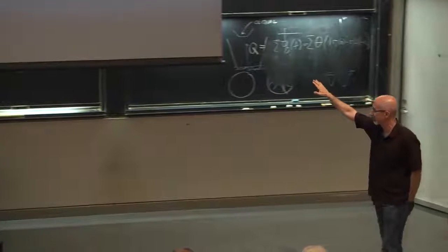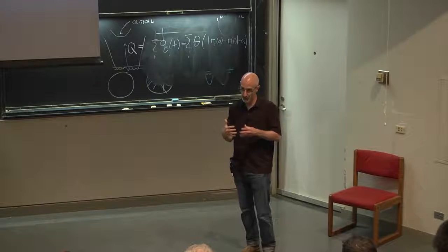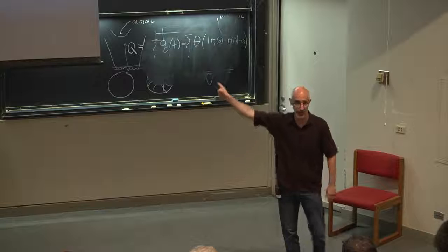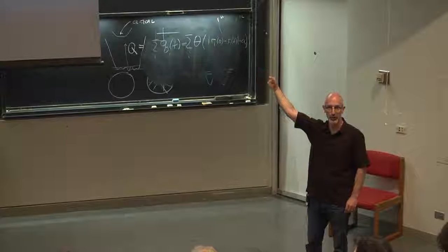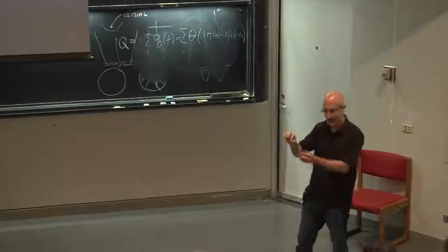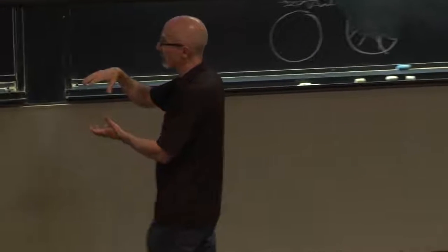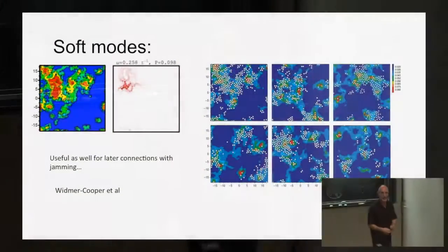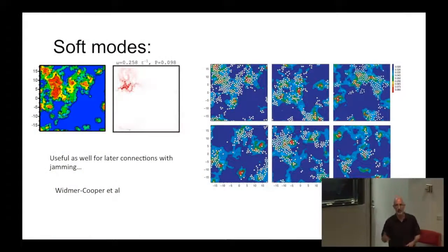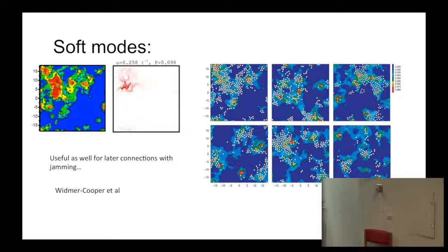So the thing that's interesting here is one of the primary tools for understanding, let's say, the length scales that might diverge at the jamming threshold are actually looking at, let's say, the structure factor associated with the transverse component of these mode structures. And near the jamming transition, because of the isostatic nature of the particle configurations, these length scales may diverge or will diverge. Here, we don't see anything like that, but what's quite interesting is the particle motion can be decomposed in a way where there's a correlation between the soft mode structure and where particles move.